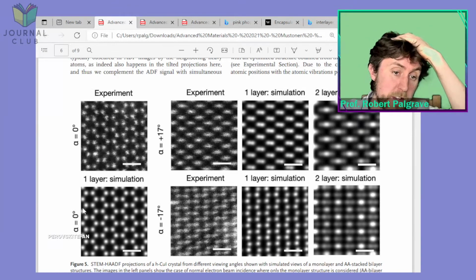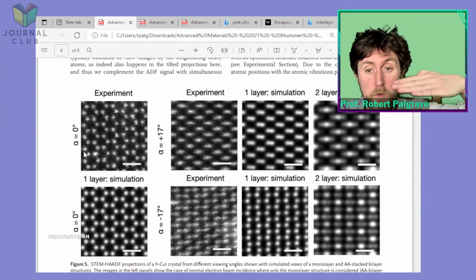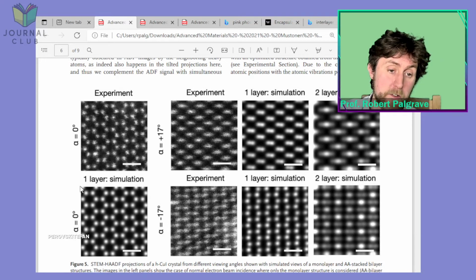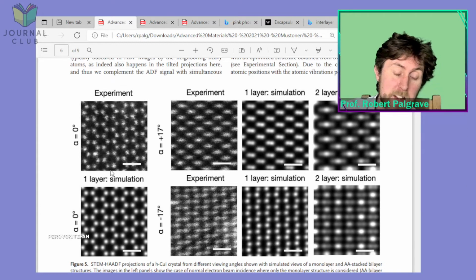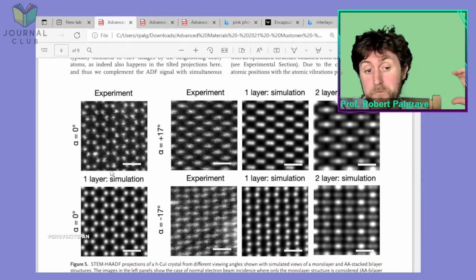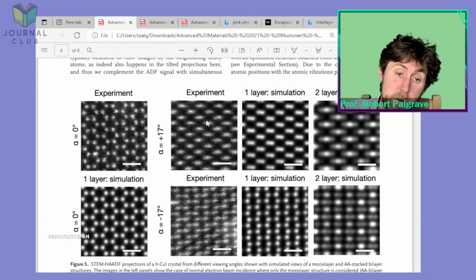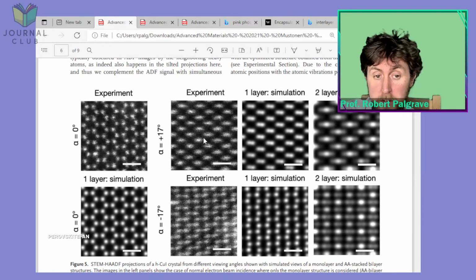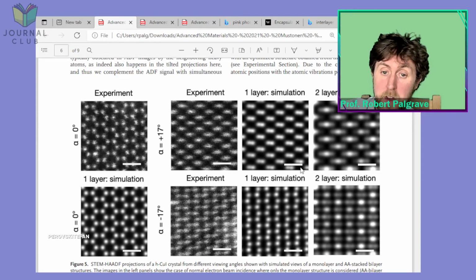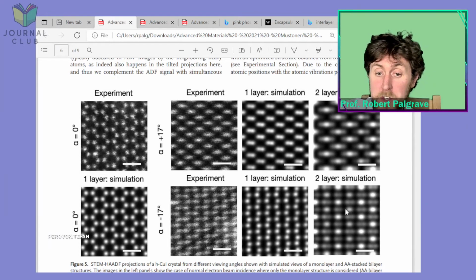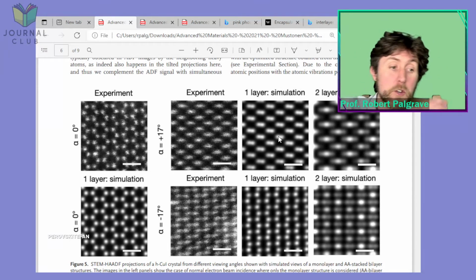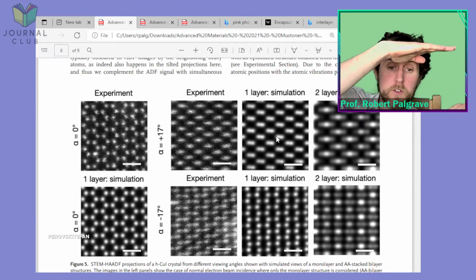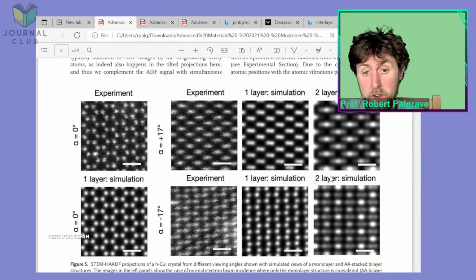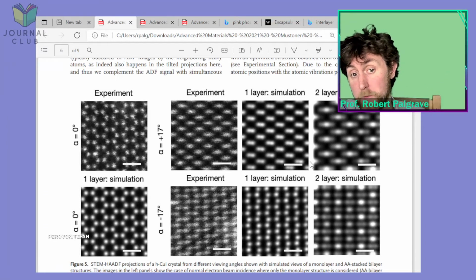And they use different tilt values here. So they tilted the sample relative to the electron beam, relative to the image that you're seeing. And here at 0 tilt, so we're looking straight down on top of it, this is what the experiment looks like, and this is a simulation if we had a single layer of this cuprous iodide inside. Then they did a tilt experiment, so plus 17 degrees, minus 17 degrees, and here's what it looks like in the experiment. If you had a 1-layer simulation, if you had a 2-layer simulation. So they want to test the hypothesis, do we only have 1 layer inside, or do we have multiple layers inside the graphene sandwich? Do we have a single decker sandwich, do we have a double decker sandwich?